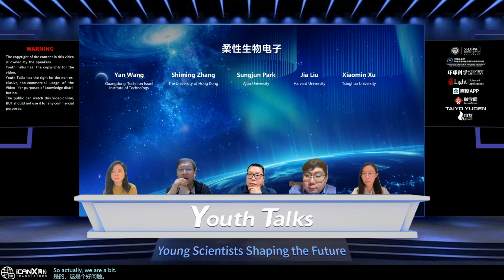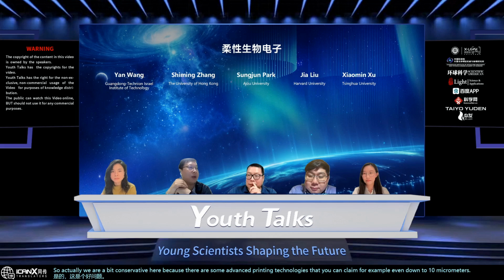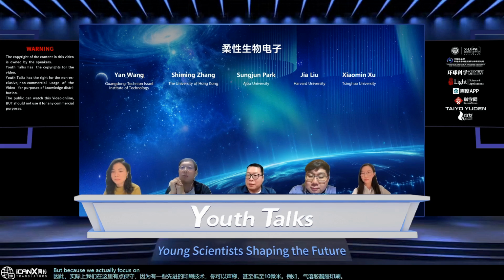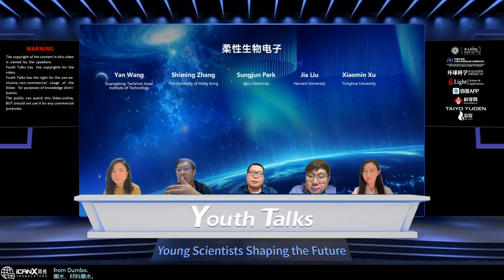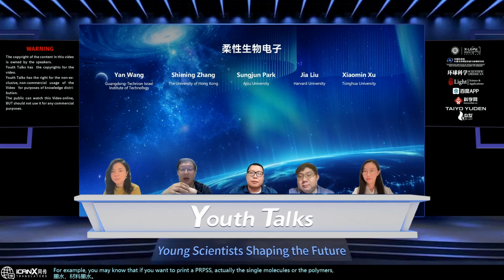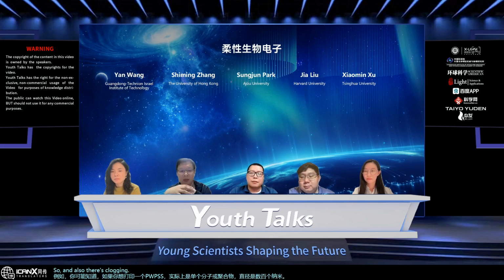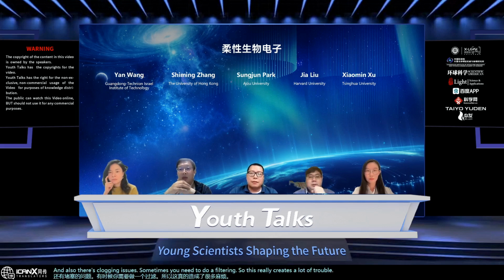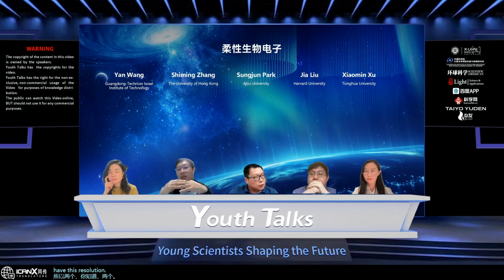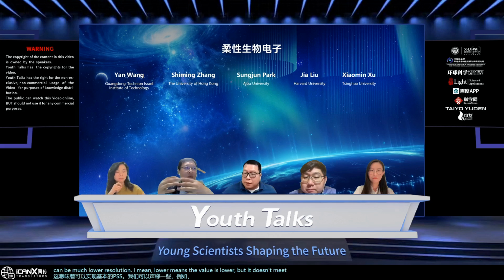We are a bit conservative here because there are some advanced printing technologies that can claim, for example, even down to 10 micrometers, such as aerosol jet printing or many others. But because we focus on one-shot printing of multi-channels, it depends a lot on the material ink. For example, if you want to print PEDOT:PSS, the polymers are hundreds of nanometers in diameter, and there are also clogging issues, so sometimes you need filtering. This creates a lot of trouble. So this resolution is the threshold resolution for all these materials. PEDOT:PSS can achieve it; for silver, we can claim a much lower value, for example 10, but that doesn't meet the requirements for all the materials.